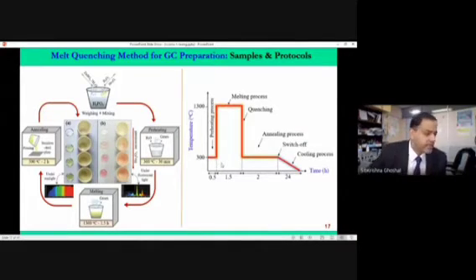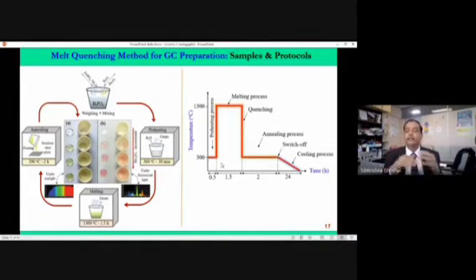So the heating and cooling schedule means at what temperature we heat, shock heat, then we quickly quench, that means we cool down very fast, then again slowly heat, then anneal, then we cool finally to room temperature. This temperature schedule is very, very important to get the right crystallinity. Maybe we want 25% crystallinity. Some of you can tell, no, not 25, 18% crystallinity, the rest is amorphous glass. So this tunability of the glass and crystallization requires very complex temperature scheduling, which is called the cooling heating effect, and that we are trying to do.